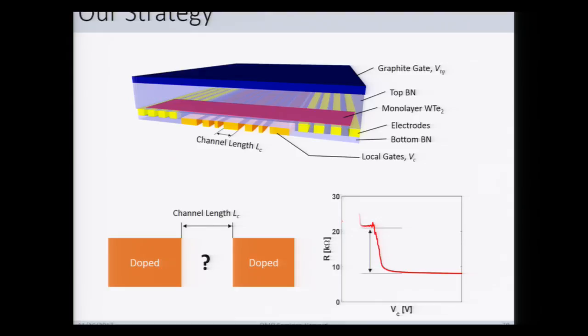But instead, what we see is an approximate plateau that, where I've drawn these lines, is a difference of resistance, this step height, which is approximately half of the quantum of resistance, which is strongly indicative of having a single helical edge mode at each edge of the sample. And here we have two. So let's zoom in on that.